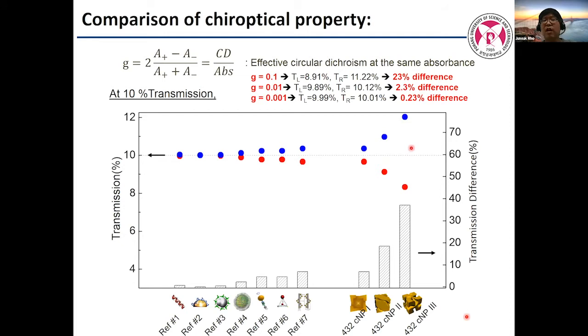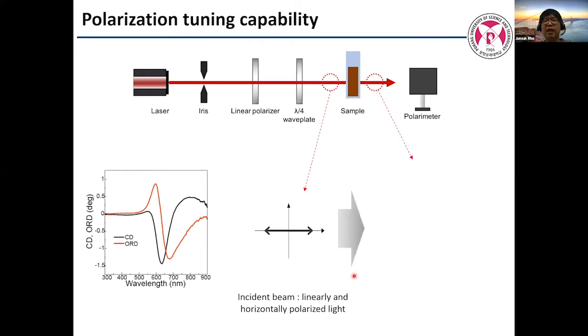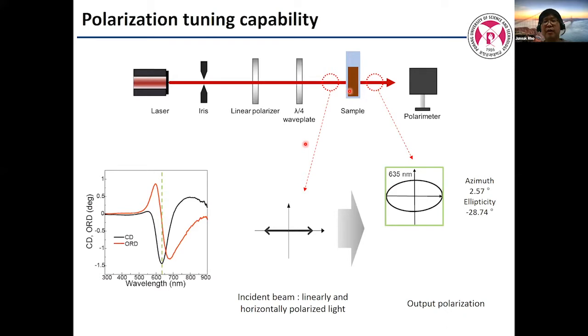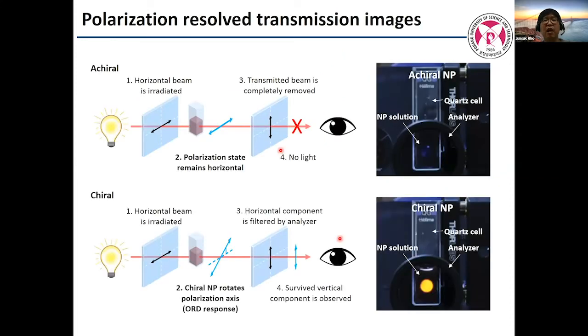So what can we do? A 10 times larger G factor means a 10 times larger difference in absorption between left-handed and right-handed light. One example is changing polarization. Linearly polarized light comes into a nanoparticle, and the azimuth angle and ellipticity are changed by this optical rotation. Even more interesting is plasmonic color. With a normal nanoparticle, linearly polarized light just passes through, and with a vertical polarizer, nothing comes out, so no color. But in the chiral particle case, there is optical rotation, so the horizontal light is rotated and some portion comes out. So we see some color.